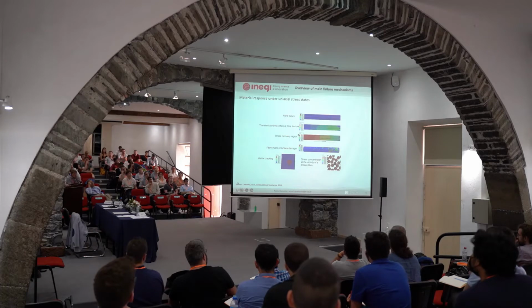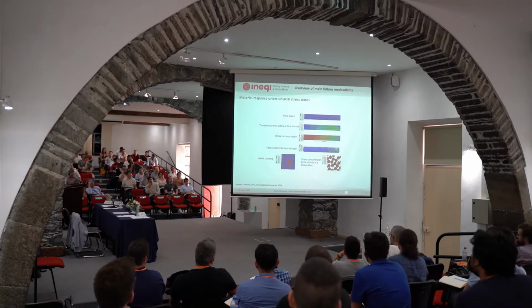Okay, so this is just for one fiber, but of course we can simulate this for a composite with direct numerical simulation, where this is a dynamic model because, of course, you have a dynamic effect associated with fiber fracture. This is a little bit busy, so I will try to isolate the mechanisms here. For example, this is one fiber that we took from the fundamental model that broke there. So we have a continuous damage model for the fiber.